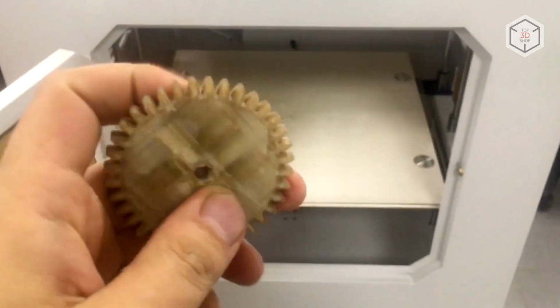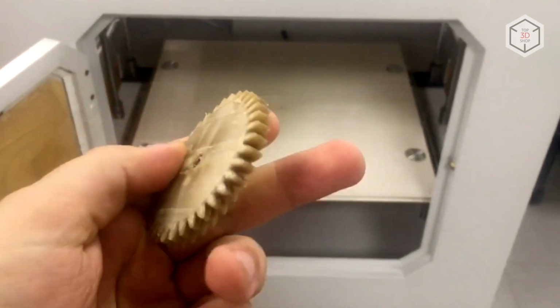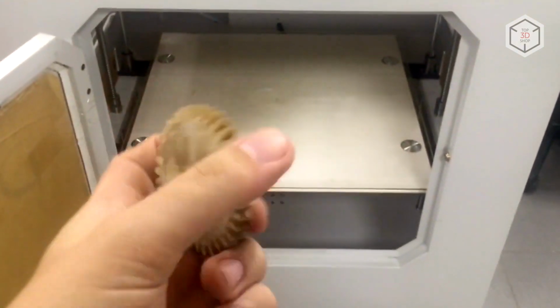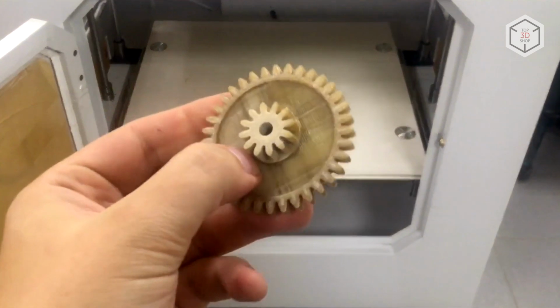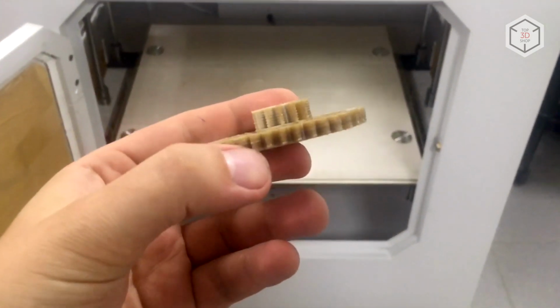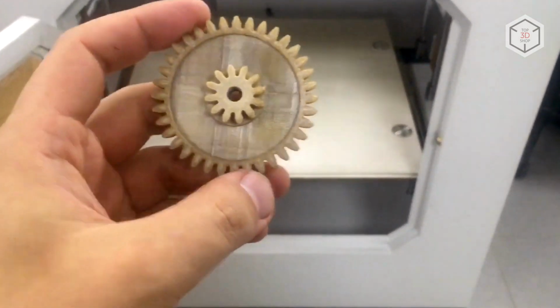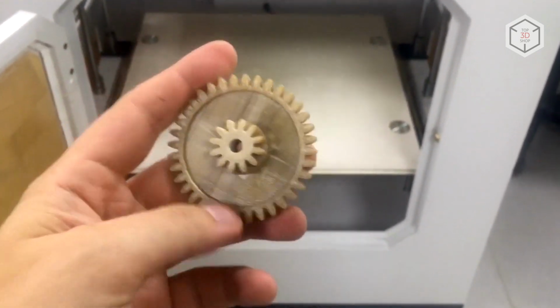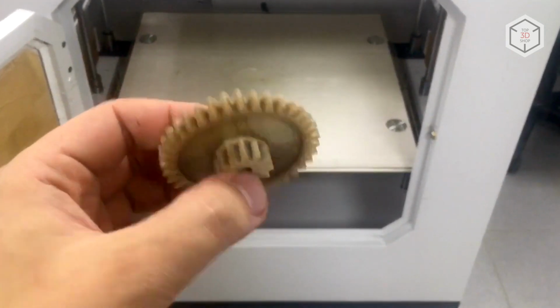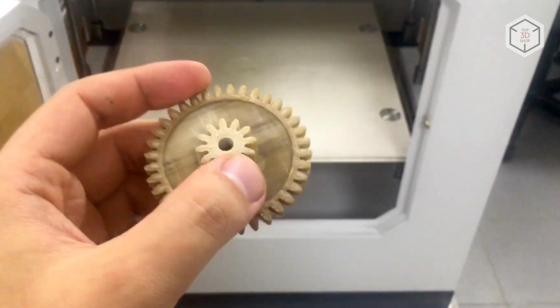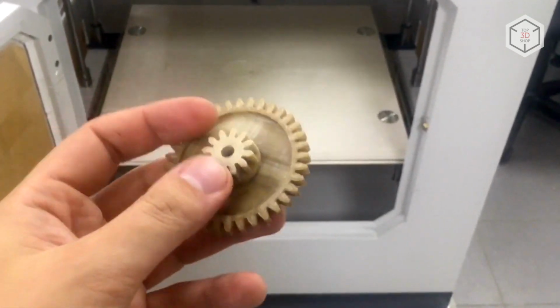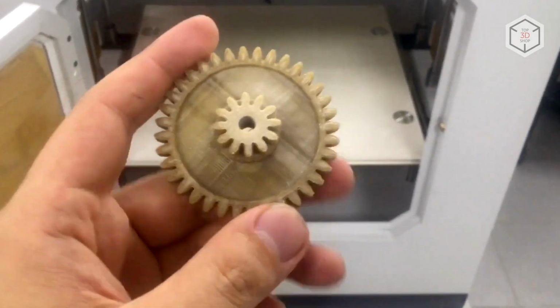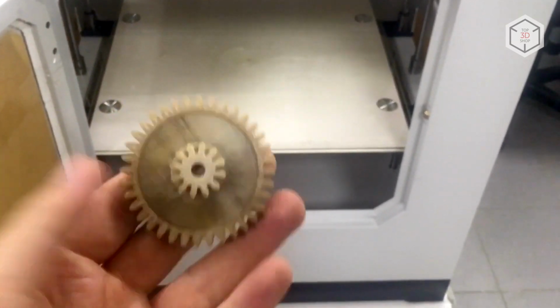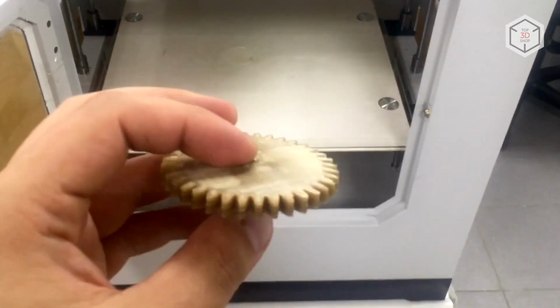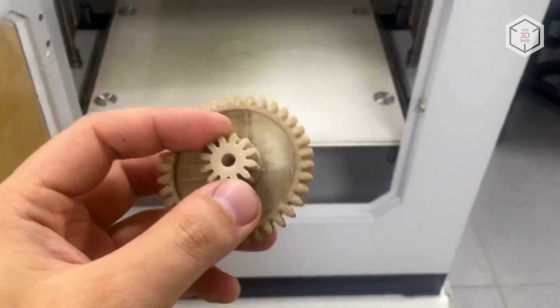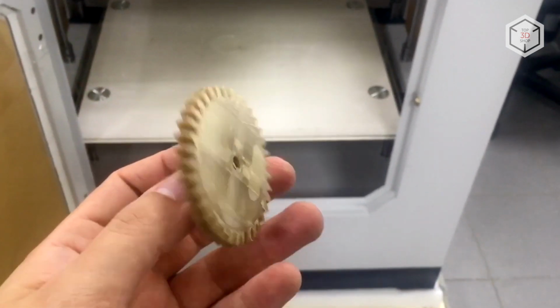Judging by the appearance, the gear turned out to be very durable. We can already give some recommendations with regards to the print settings. If you plan to print small parts like this gear, choose a layer height of 150 microns. If the size of the object is larger than 20 centimeters, it is recommended to print with a 200 micron layer thickness. Note that printing with PEEK can be difficult and is not always successful without extensive experience. We would recommend getting started with more compliant plastics like ABS and PLA, and then move on to high-temp materials.